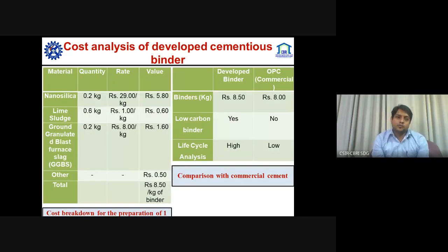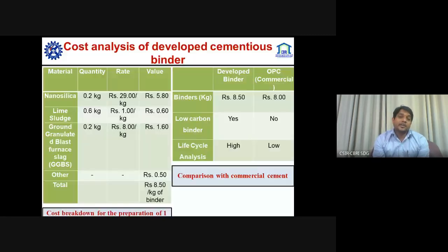And when we do cost analysis of developed cementitious binder, it was very much comparable with the commercial OPC, as you can see it is 8.50 per kg of binder, which is very much comparable to the commercial OPC, and the cost of developed binder can be further decreased with the bulk manufacturing or with better technology, with better instrumentation for this developed technology.